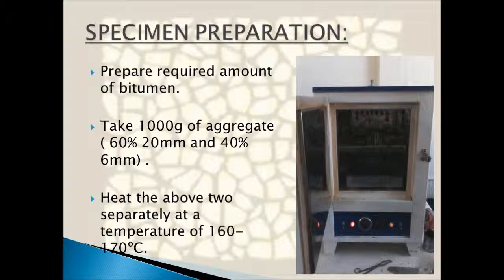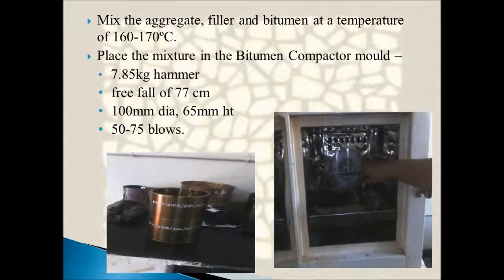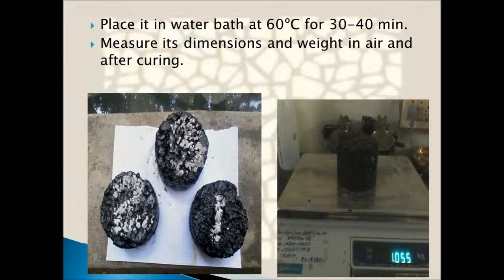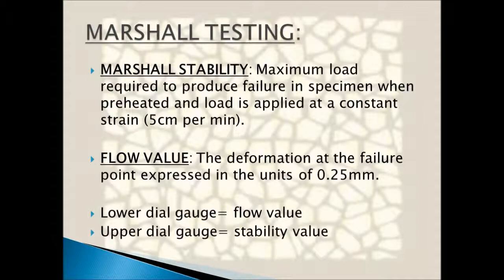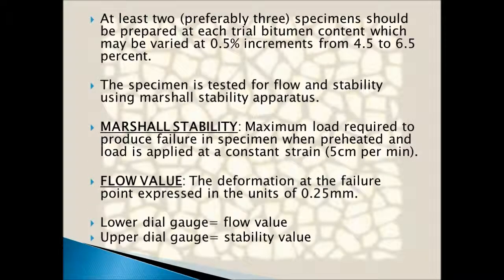The slides show the readings. Next, the optimum bitumen content is to be found out. It is determined by plotting the following graphs: unit weight vs. bitumen content, Marshall stability vs. bitumen content, voids in total mix vs. bitumen content, aggregate voids filled with bitumen vs. bitumen content, and flow value vs. bitumen content. All these graphs indicate that when there is an increase in bitumen content, these values also increase, but after a certain value of bitumen content, they decrease.